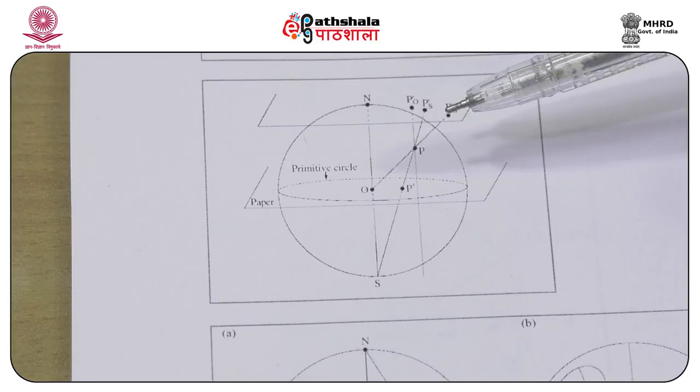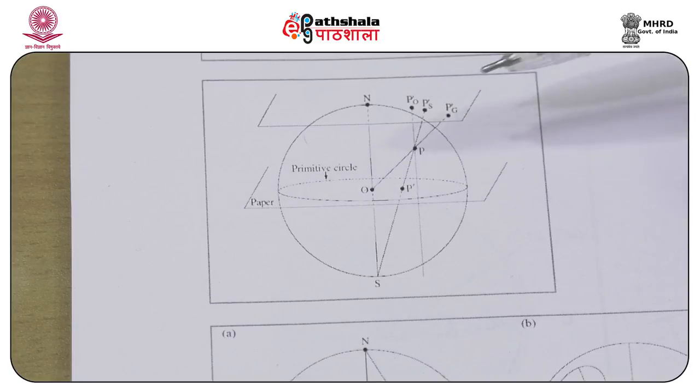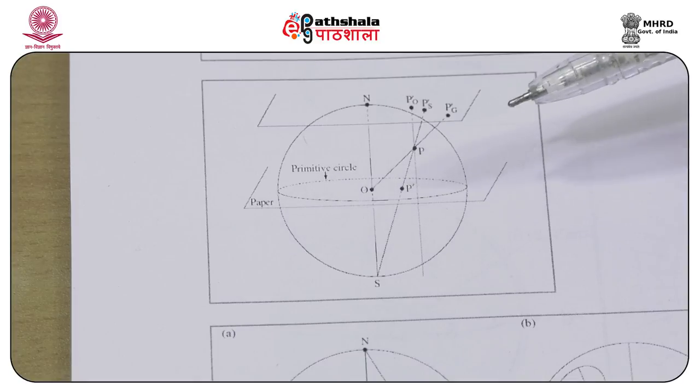Both these projections have their individual uses in crystallography. The orthographic projection is useful for visualizing crystal shapes, and the gnomonic projection is relevant for labeling electron backscattered diffraction patterns which we obtain using scanning electron microscopes. However, neither of these projections is conformal, that is, the angles so projected are distorted in these projections. In the beginning of the class itself, we discussed that the stereographic projection is a conformal projection, that is, the angles between faces or directions will not be distorted in the case of stereographic projections.